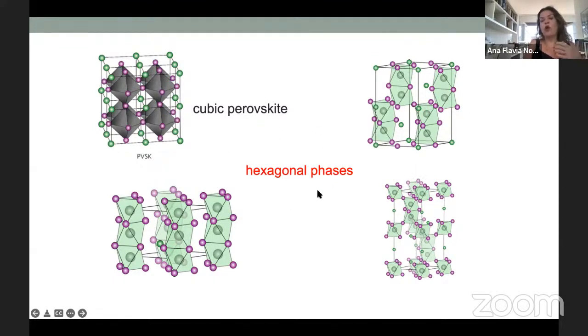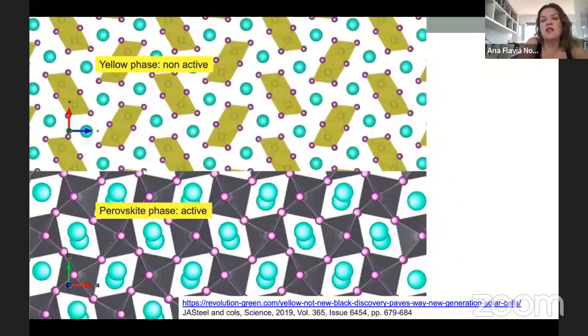But it's really hard to not form other phases, what we call hexagonal phases, especially because these hexagonal phases are more thermodynamically favorable to form instead of the cubic perovskite. And you don't want these hexagonal phases. Okay, why don't you want the hexagonal phases?